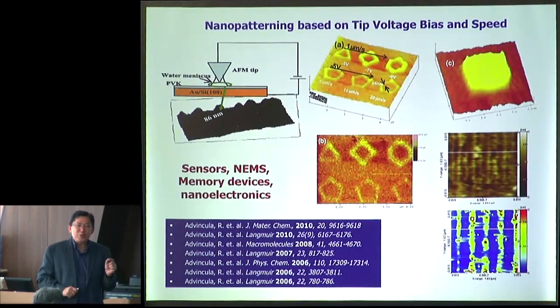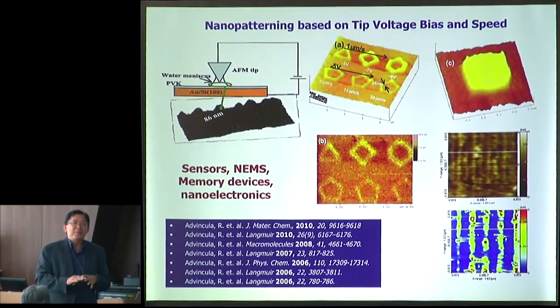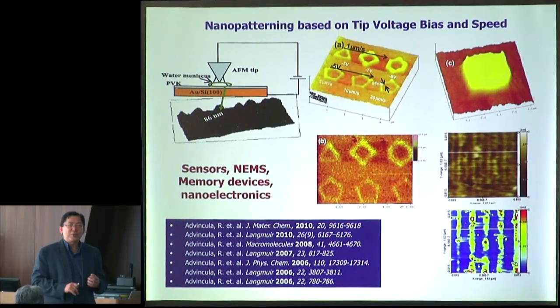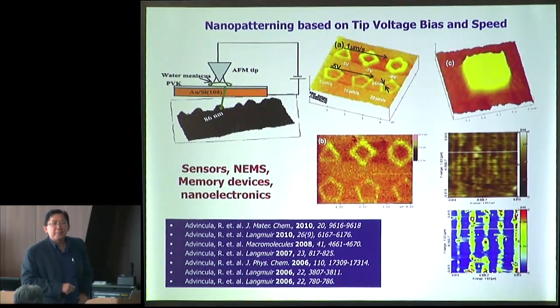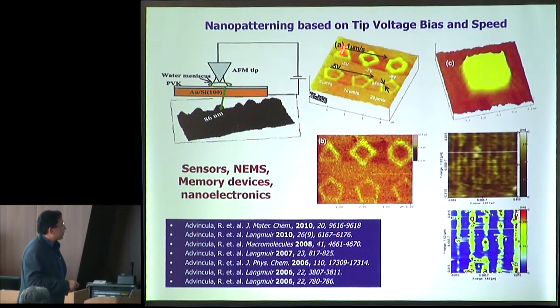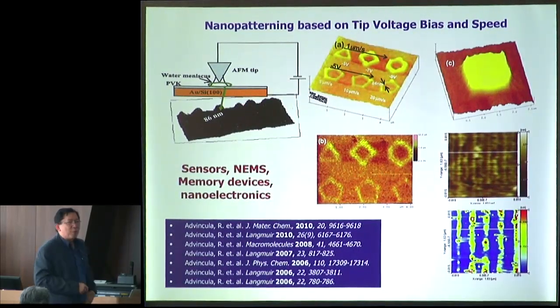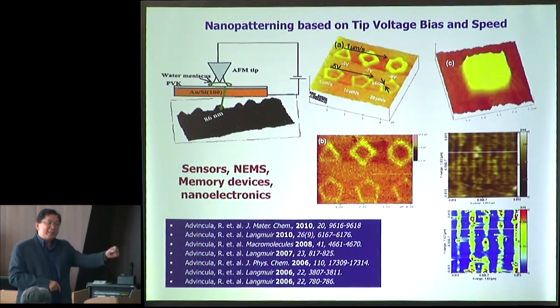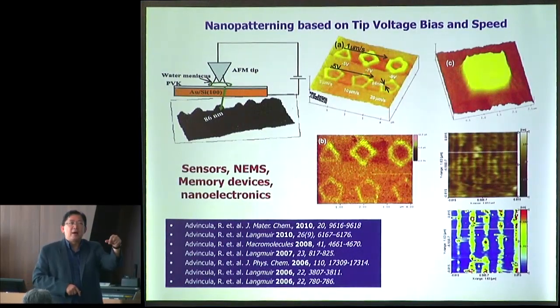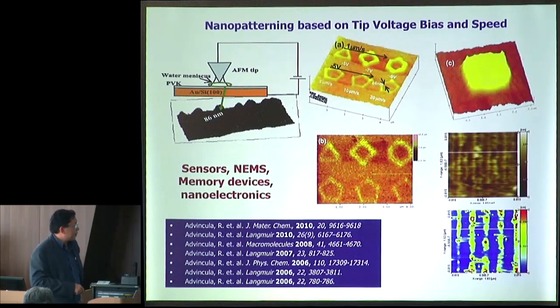But one thing I like to do with your student, I like to spin coat polyvinyl carbazole on gold. And then we want to test an AFM tip that's conducting. And then we move that tip on the PVK, and let's hope we can see a pattern. So we actually did a quick and dirty experiment, and lo and behold, we get patterns of about sub 100 nanometer lines, all by simply moving the AFM tip in a conducting AFM experiment.